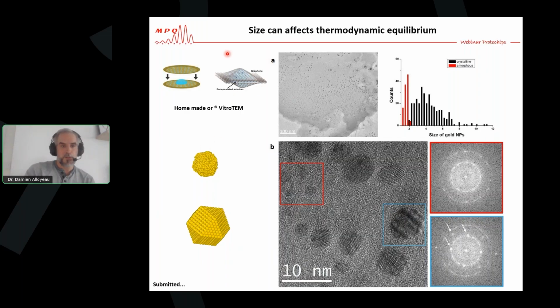So we designed an experiment using a graphene liquid cell. And here you observe the graphene liquid cell just after the first second of observation within the TEM. So we have again just the chloroauric acid solution within the liquid cells. And here you observe that just after a few seconds, the great majority of the molecules, the gold precursor, have been reduced, and you have this population of nanostructures.